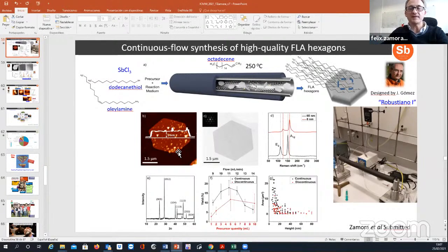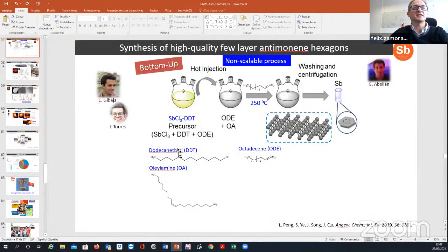It's complex, because if you focus on this reaction, as I told you, this is a flash reaction, and as you raise the temperature up to 250 degrees, the time that you have to reduce this temperature in a short time is not trivial to adjust. And as you open this time window, then you enhance the thickness. So this is a big problem. We want to do something in order to go down, but still we are playing with the experimental conditions.